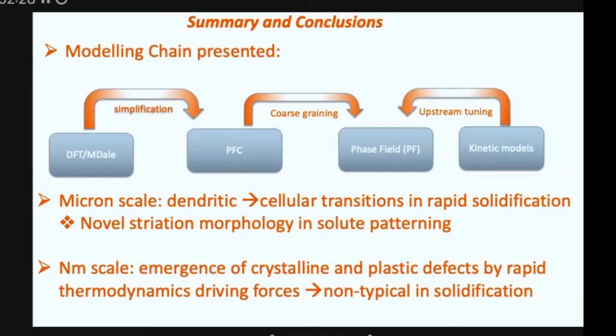Another thing that these voids often do while they're forming is they can trigger the nucleation of a secondary phase that wasn't going to be there if the void didn't sort of lower the barrier as a heterogeneous site in its own right. And so for the striations, I don't know, but for the voids, I know they are a problem. Can you guess what the striations might do to the structural stability? I think if anything, if the cooling rates where the striations are just chemical, they actually may help in the strength because they create more barriers to dislocations to move through. So they may actually be a beneficial thing. I know they're going to be a beneficial thing in some sense, but I don't know how ubiquitous it's assumed. Because right now, a lot of this is just very empirical. People haven't really classified this in a way that, you know, we have dendritic growth, even numerically.